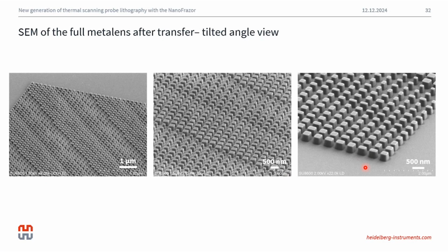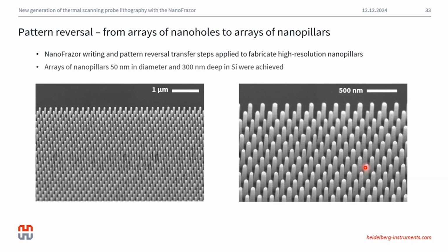And of course, this pattern transfer method, which took us from holes to rectangular features, can be applied to more high-resolution features. And we can apply this method to go from arrays of nanoholes to arrays of nanopillars. Using the same microfabrication steps, here we were able to achieve nanopillars that are 50 nanometers in diameter and 300 nanometers deep into silicon.